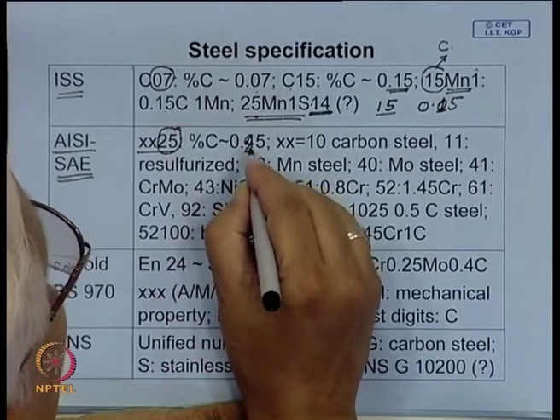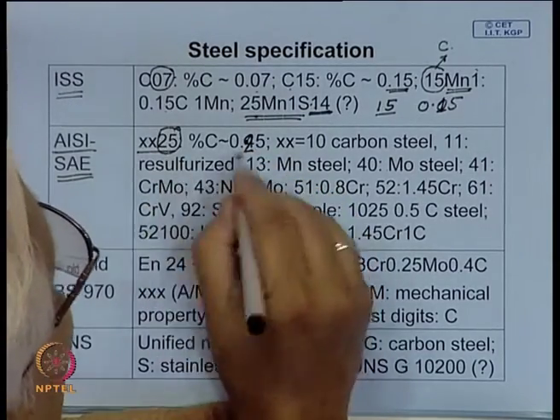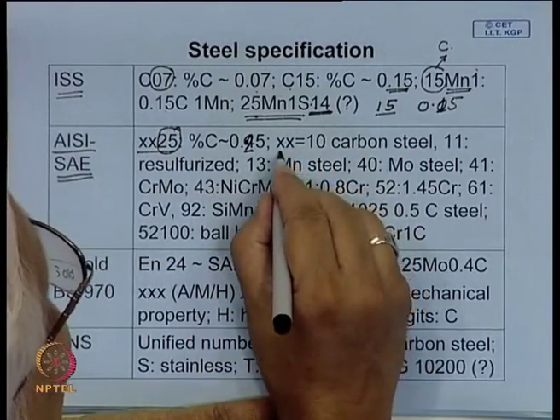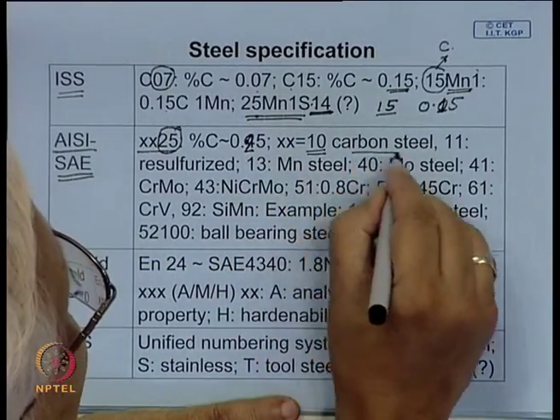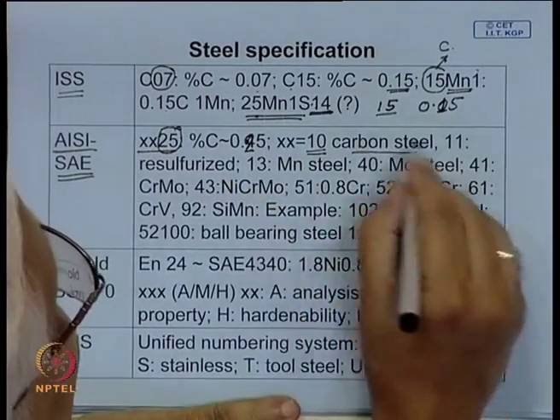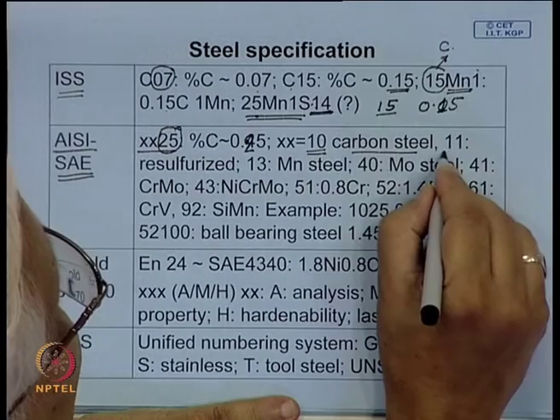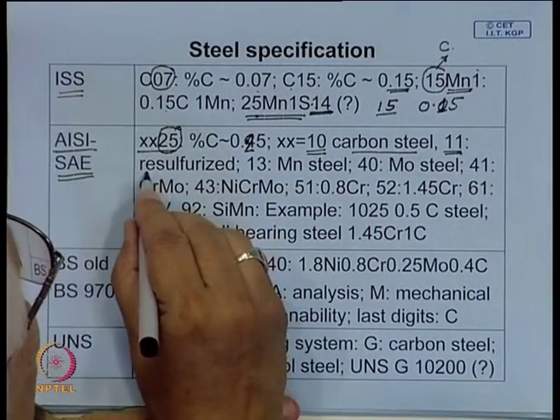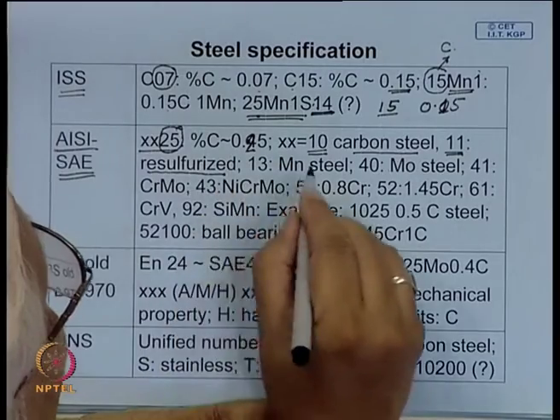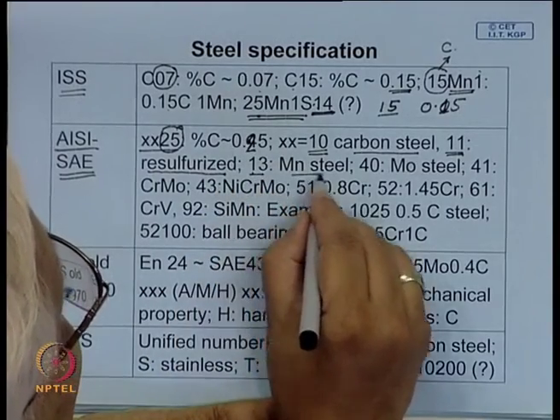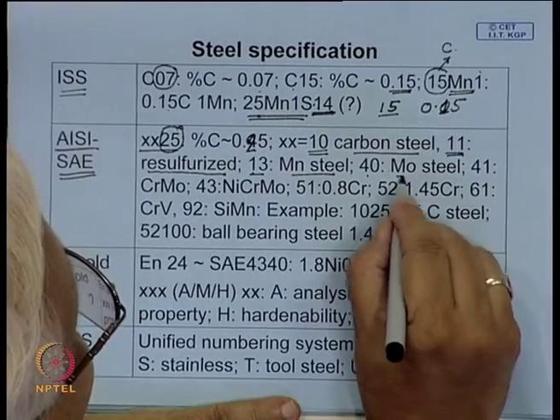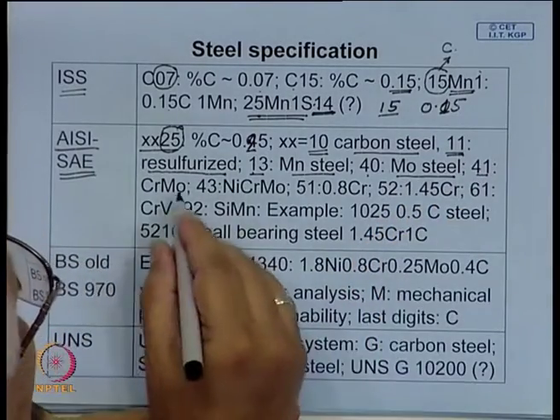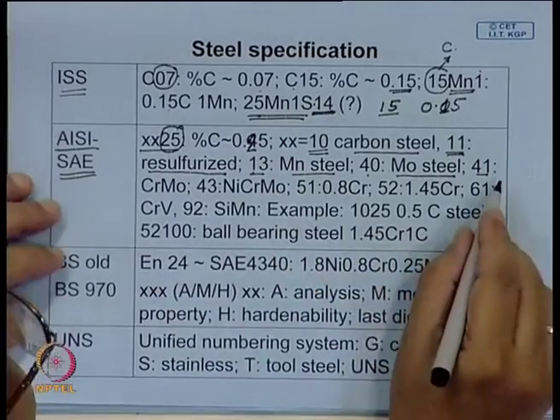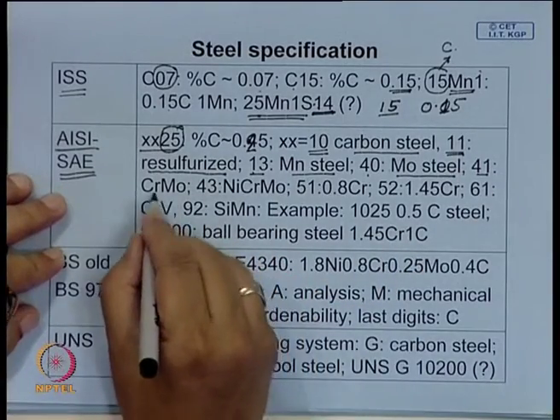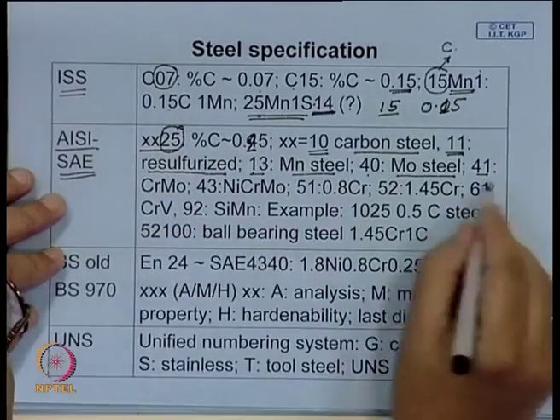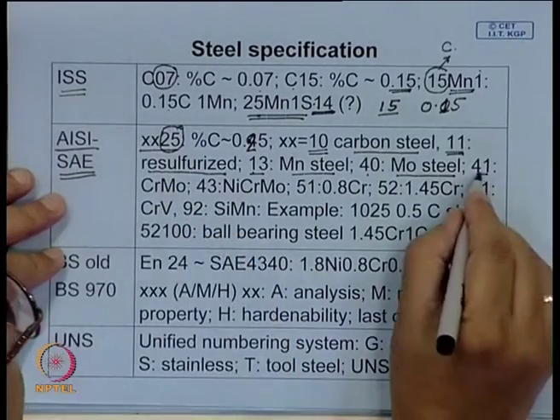There is a mistake here. This should be 0.25 as the carbon content, and this XX, if it is 10, means plain carbon steel. The first 2 digits, if it is 11, is resulfurized steel. 13 means manganese steel. 40 means moly steel. 41, this is the convention, there is no basis, but if you follow this convention, it is possible to guess what the composition is and what the major alloying elements are.